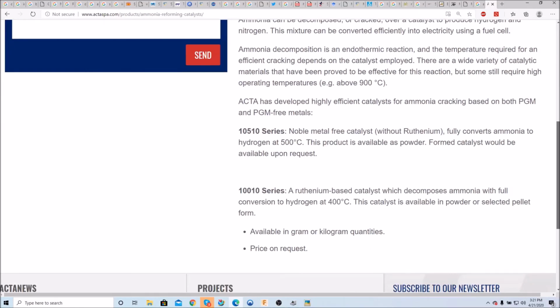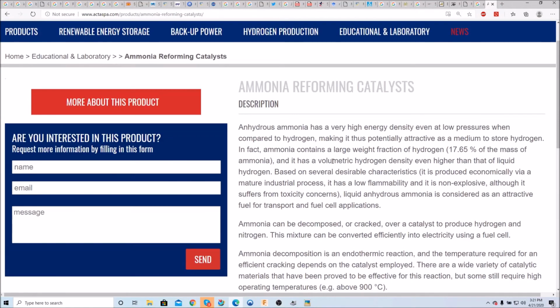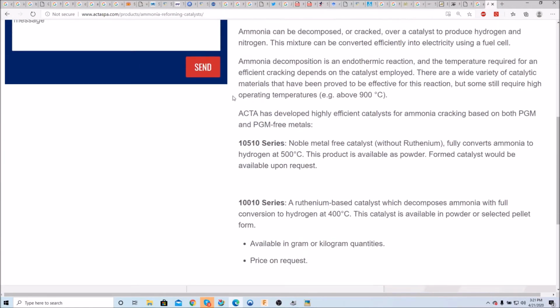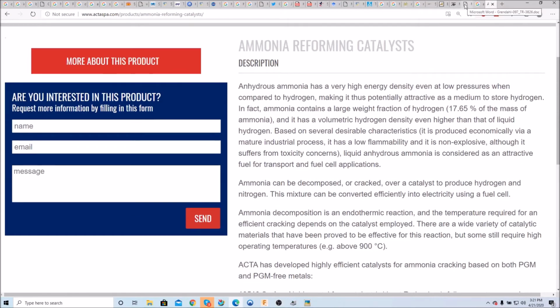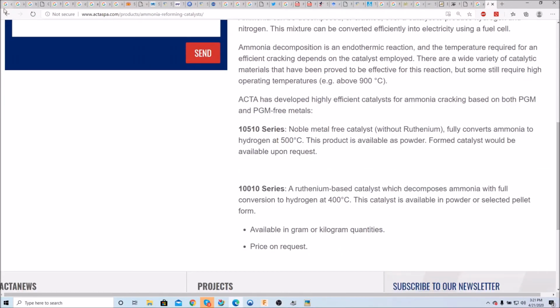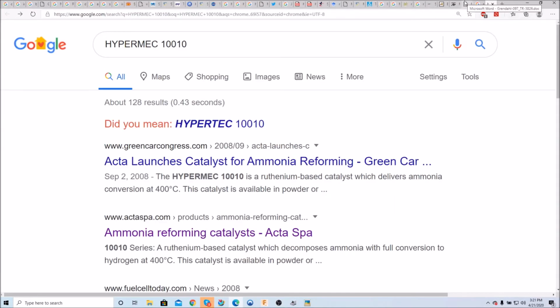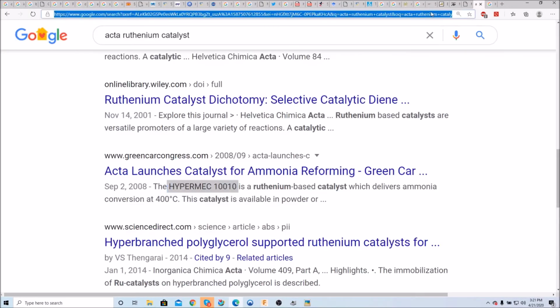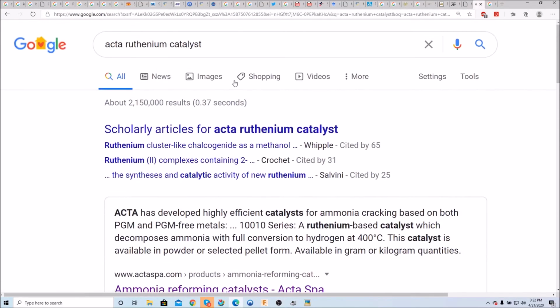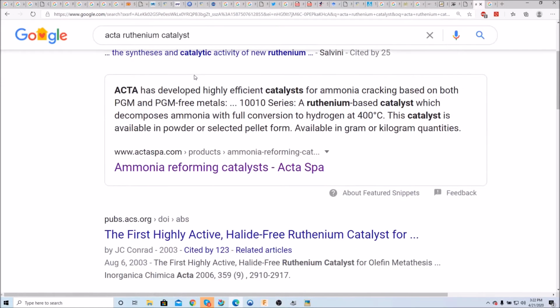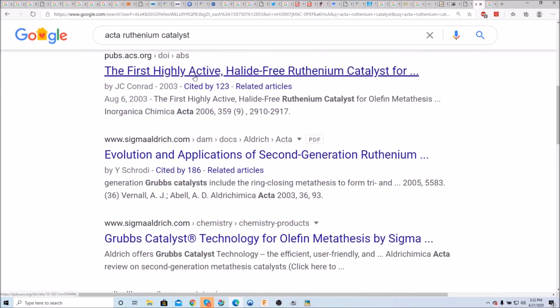Okay, so the price, they have to distribute the ruthenium on the aluminum oxide. That adds cost, but the actual cost of the raw materials is very small. I mean, if you're talking about 1 gram, right? $8 a gram. That's $8,000 to crack 1 kilogram of hydrogen per hour. Now you assume, well, it's going to be a lot higher than that because you're going to have to place the ruthenium on the aluminum oxide, right? You're going to have to mix the ruthenium with the support, right? A catalyst has to be supported.